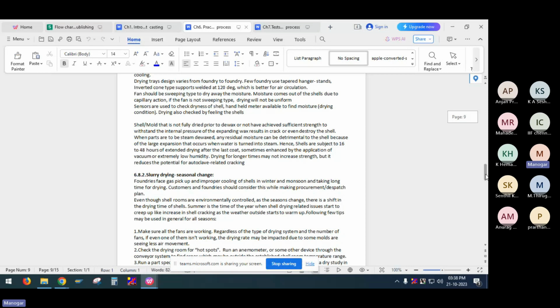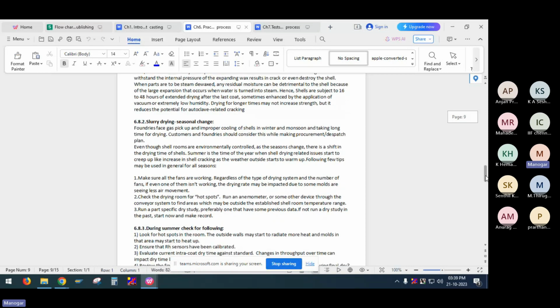If the molds are not dried properly, at de-waxing time it will be a problem and will lead to cracks. And slurry drying also you have to consider for the seasonal change. Depending on the seasonal change and humidity, you have to prolong the drying time.